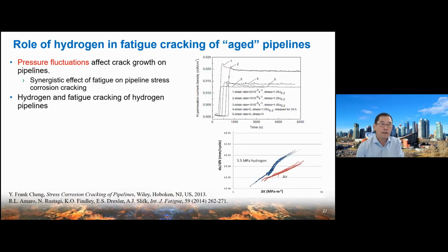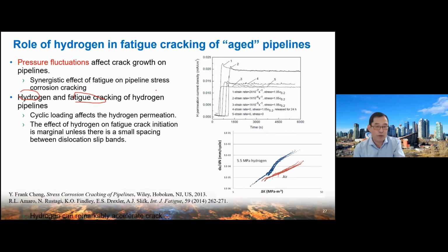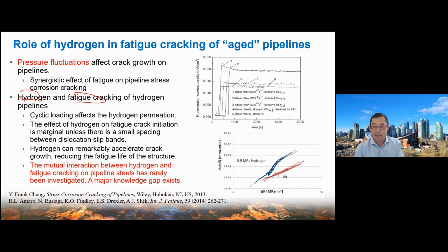Number three, pressure fluctuation always happens in gas pipelines. For the natural gas pipeline, we do research stress corrosion cracking in terms of pressure fluctuation. But if hydrogen is introduced, how will the hydrogen and the fatigue cracking interact together to speed up crack growth? You can see, from these two figures on the right side, if the pressure fluctuation changes the local strain, hydrogen permeation will go up. At the same time, if hydrogen is available, when hydrogen and fatigue cracking interact together, you can also see the crack growth rate will also go up significantly.